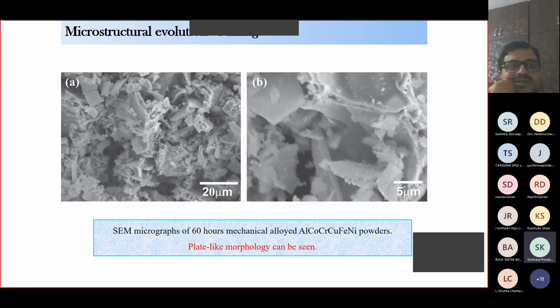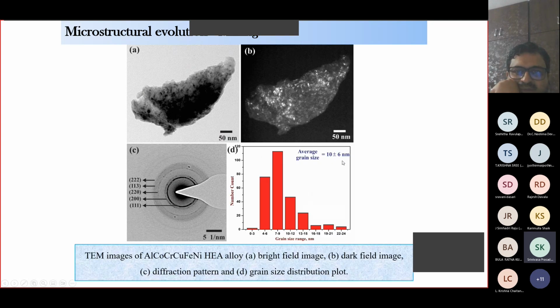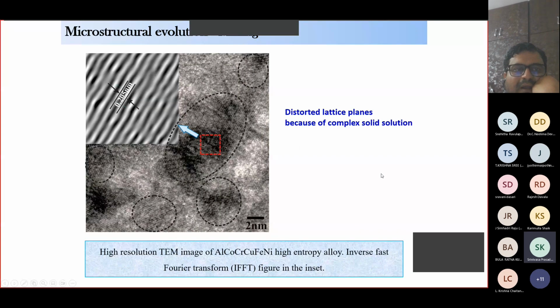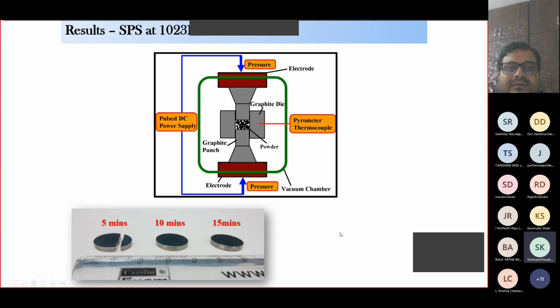Coming to the powder morphology, you see some kind of plates here after ball milling. Nice plates. You see, this is an unusual structure. And the grain size is really small, about 10 nanometers. The average grain is 10 nanometers. And you have the presence of a single phase structure, although there are several elements. And when we try to measure the interplanar spacing, that corresponds to the one that we measure using the X-ray line profile analysis. And to understand the mechanical properties of these materials, we have to compact them into bulk discs.